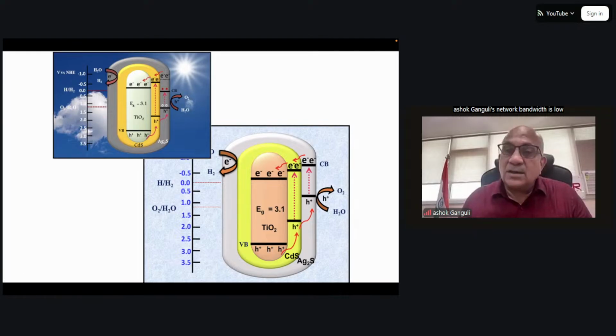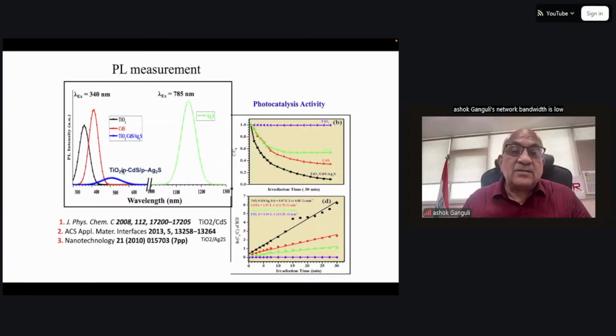And you want a barrier because you don't want electrons and holes to recombine. So the lifetime will increase as long as barriers are increased. And you can see that for the case where you had N and P type, the photoluminescence efficiency goes down, which tells you that recombination is less, hence luminescence is less. That means you have more long-lived charge carriers.